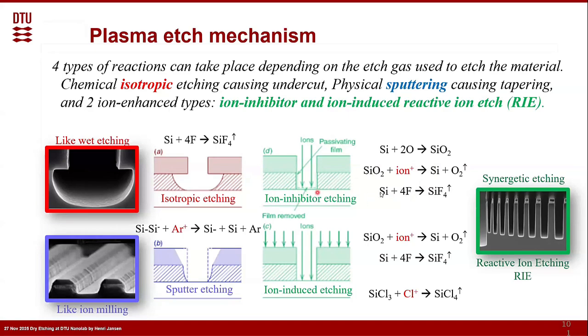So normally this ion inhibitor etching is much faster and more directional than the ion induced. The disadvantage, though, is that you have to control this one very well because it is really a balance. If you do a little bit too much, you will get undercut. We will see that later.